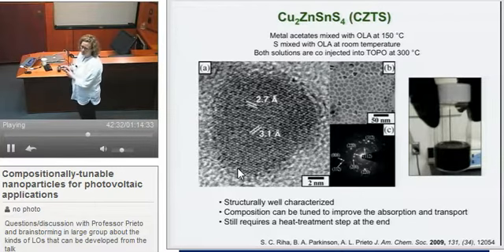So what we decided to do was to try to initiate the precipitation of this compound using a change in oxidation state. We started with metal acetates mixed with oleylamine, which is a very long chain primary amine that has a double bond roughly in the middle. That might actually be important for the reaction. And what's important here is we start with copper 2+. Oleylamine is known to be a reducing agent at elevated temperatures, so we are trying to go from copper 2+ to copper 1+ to start the reaction.